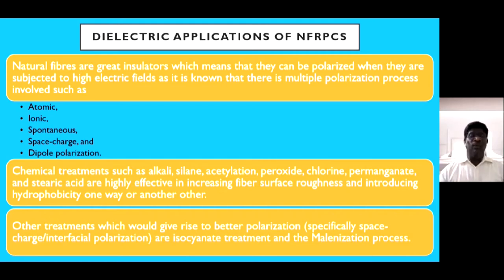Chemical treatments of wood like alkaline, silane, acetylation, peroxide, chlorine, permanganate, and stearic acid are highly effective in increasing fiber surface roughness and introducing hydrophobicity one way or another, so that it can increase the dielectric constant value. Apart from this, other treatments could give rise to better polarization, especially space charge and interfacial polarization, such as isocyanate treatment and maleation process. This process increases the polarization ability of natural fibers as well.